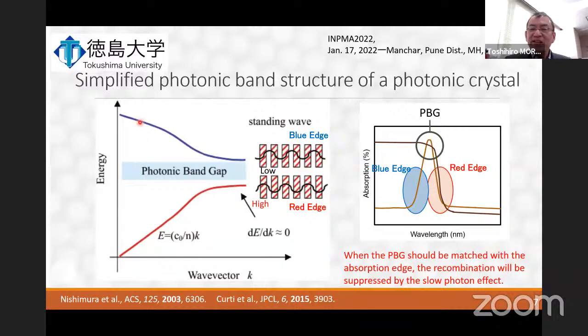At the energies above the band gap or stop band, from the blue side, the standing wave is predominantly localized at the low refractive index part, which is the air void or something. These photons with reduced group velocity are termed slow photons.